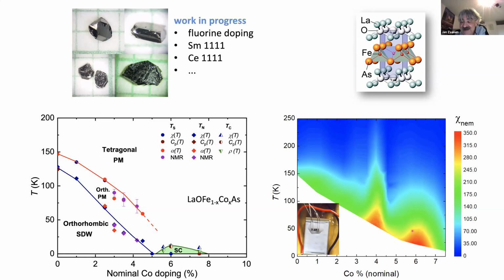Having said that, when you have the lattice and there is disorder, right? You do expect that you get a sort of puddling, having orthorhombic domains that are messy in a tetragonal background. Right, so if you could switch off the electron-phonon coupling, it could be that you would have a very neat second order electronic nematic transition. But it's in fact obscured because you see it indirectly through the lattice, and the lattice feels a lot more of the disorder than the electron system does. The electrons are self-averaging, right? They're self-annealing, they're very quantum mechanical, they're way more liquid than atoms are, so to say.